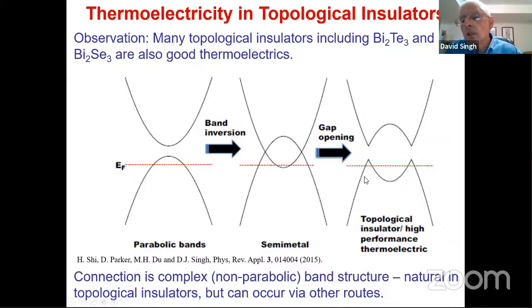But the other thing you notice immediately is that this was parabolic bands, but the shape of this band is not parabolic. It has this W shape, right? And so this is very much not parabolic, and that's very much good for thermoelectrics. And so there's the connection, is that in fact, this band is quite complex, and that's good for thermoelectrics. And so in general, we expect topological insulators to have complex, not parabolic band structures. And that's a good thing for thermoelectrics.